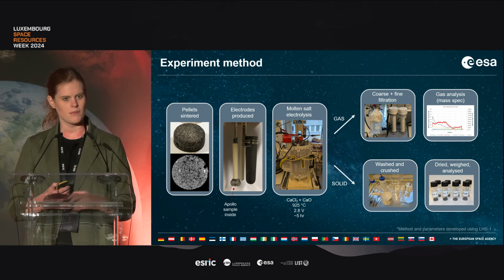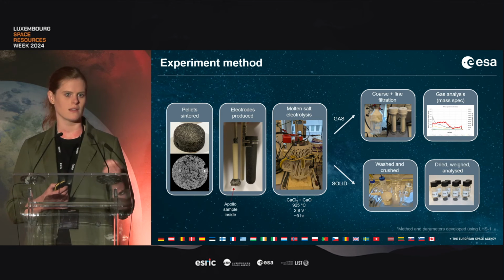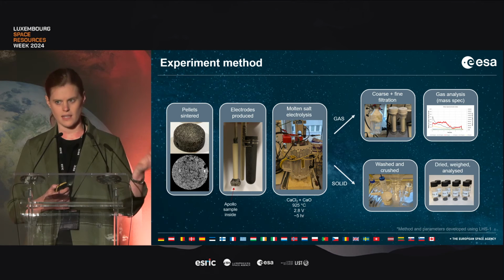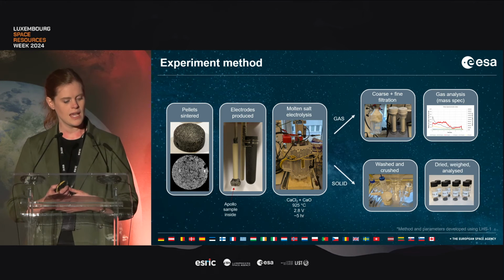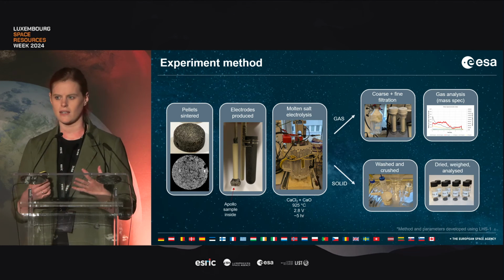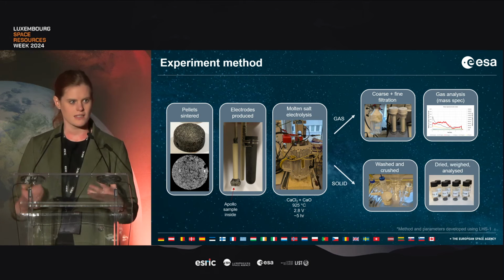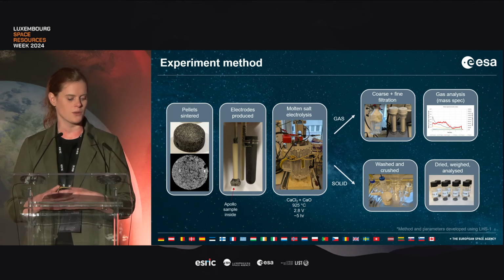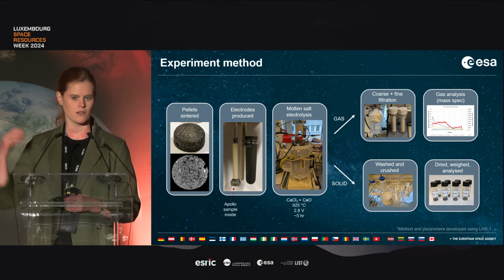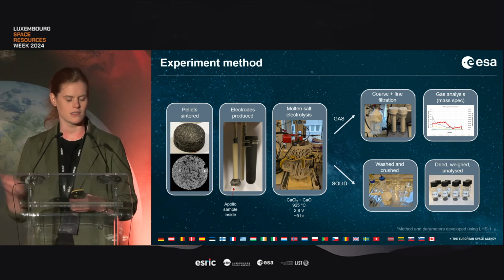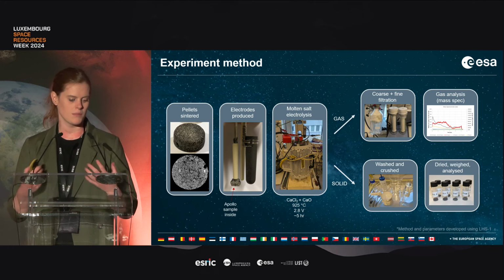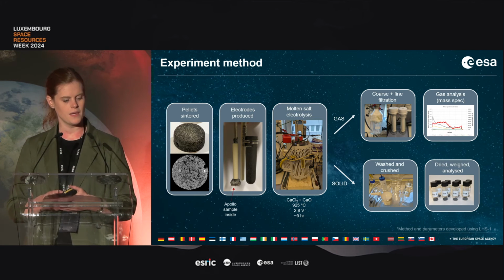This was primarily because the main goal of the experiment was to compare the behavior of the material at the cathode, the actual samples. And so the carbon anodes allowed us to have an off-the-shelf, very consistent anode. And also we weren't producing oxygen directly, which is often lost in the reactor onto the metal surfaces. So it allowed better comparability.